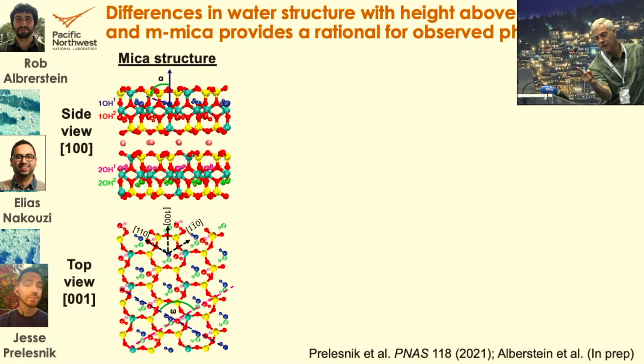So that layer's like that, the next layer's like that, the next layer's like that, the next layer's like that, and never do they point along that direction. So of the 3 equivalent directions in the surface lattice, the hexagonal lattice, one of them doesn't have OH groups pointing along it down below the layer. That's a unique direction, and that's the direction in which all those domains form when I showed you that 3 molar salt concentration where you get the smectic phase. Well, here's the surprise. It's all about the water.